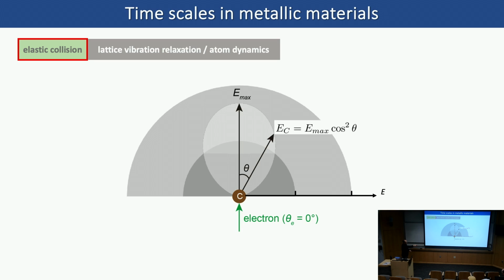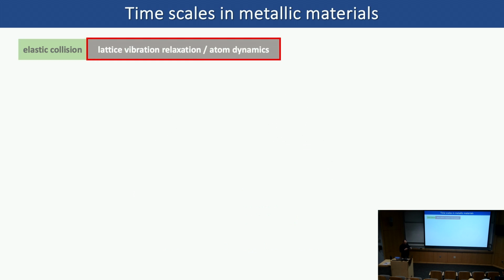So if you plot the possible energy momentum distribution of this target atom, for example, in this case it's a carbon hit by an electron, the possible distribution of energy, if it's characterized by this spherical coordinate, would look like an ovoid. So the possible distribution of that atom is on the shell of this ovoid. And this is what we call the energy momentum distribution of an atom, and you can simply call it an ovoid. This marks the possible carbon status. And then once the carbon gets hit by an electron, the lattice starts to vibrate and the dynamics start to evolve.